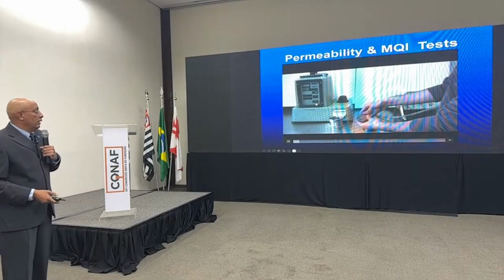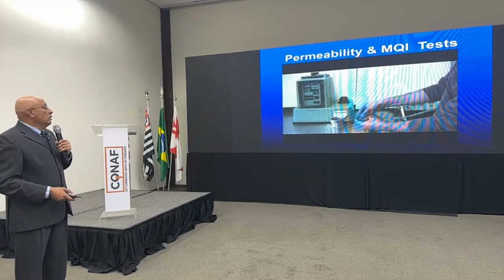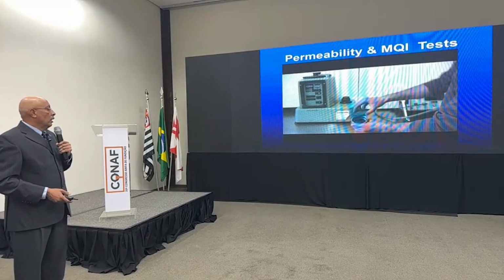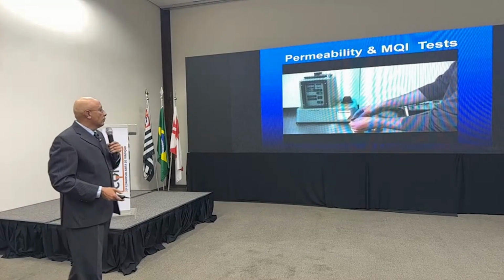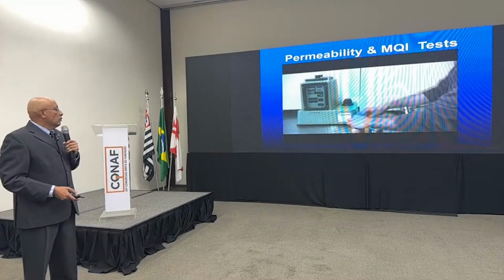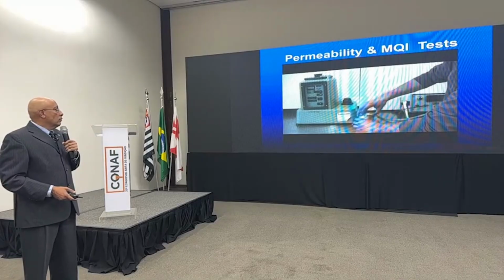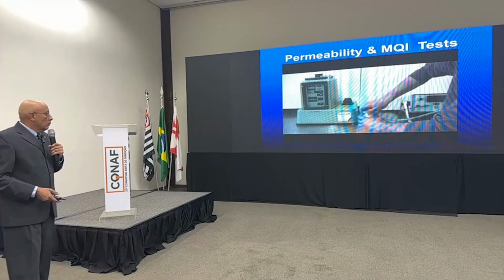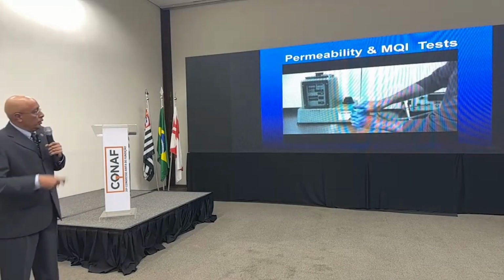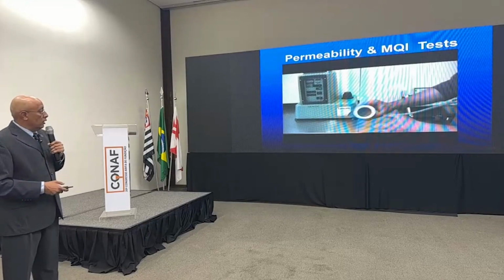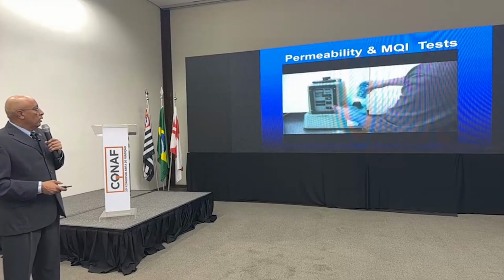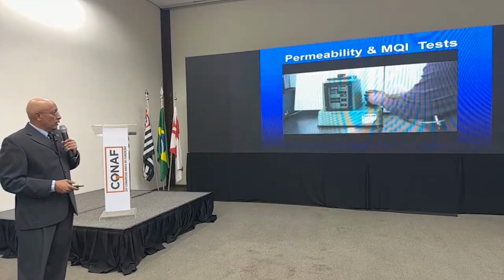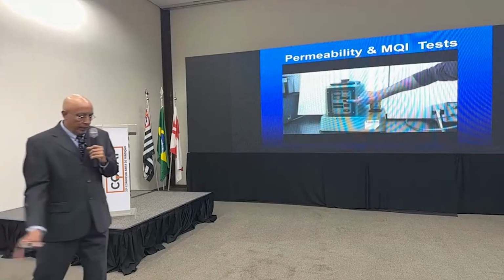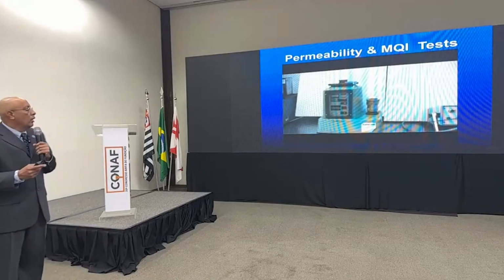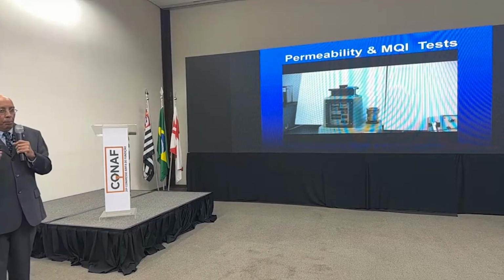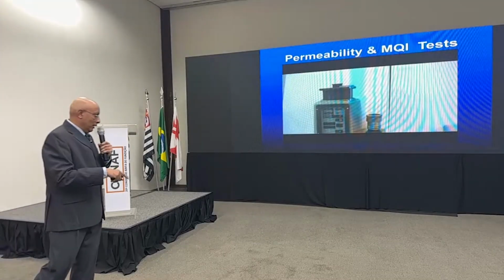So the specimen is gasketed and it's placed in a tube. This is the laboratory test. We are working to automate this technology as well. And again, we are looking at what is 2000 centimeter cube of air going through that cookie. That will generate the permeability number according to AFS.